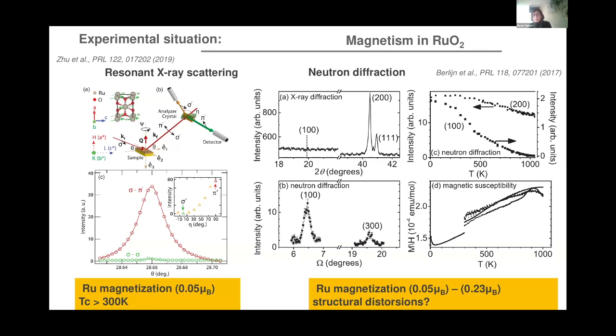Also, neutron data from the Oak Ridge group from 2017 suggest in their observations that there is this altermagnetic order happening in ruthenium dioxide at these temperatures. What I'm showing here is, for instance, the X-ray diffraction data. I should say that the resonant reflection wave vector to look at if one wants to observe this altermagnetic order is the 100 reflection. The reason is that if the magnetic ordering is along the z direction and we have the two ruthenium sublattices, which are anti-parallel, they sum up. So what we expect is a scattering along the perpendicular direction, which is the 100. That's why both experiments concentrated on this wave vector.